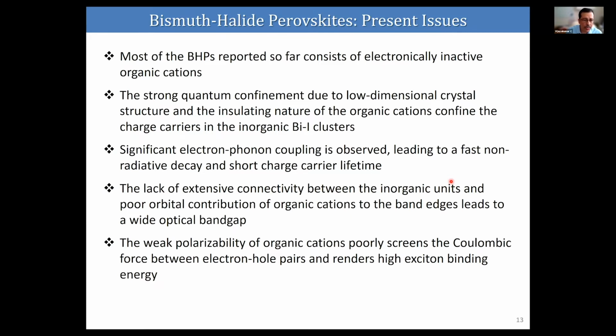Another important aspect of bismuth halide perovskites is the significant electron-phonon coupling. Because of that, the excitation energy can easily be transferred to lattice movement, and radiative decay will not happen. Non-radiative decay is promoted, and because of that the charge carrier lifetime will be very low. Again, due to the formation of low-dimensional materials, there is not much connectivity between the inorganic units. Not only that, the organic cations cannot contribute to the band edges of the material, and because of that these materials have a wide optical band gap. Another issue is the weak polarizability of the organic cation, which cannot screen the Coulombic interaction between the electron-hole pairs. Because of that, a high exciton binding energy is observed in these materials.